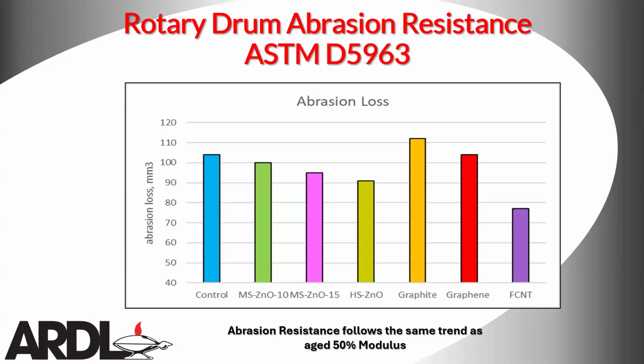But remember how I said stiffness is going to relate back to our abrasion resistance. So when we're looking at the rotary drum abrasion resistance, here we're looking at abrasion loss. So what that means is that a lower number is going to equal better abrasion resistance. And if I look here, I see the same trend. I see my higher level of zinc, my high surface activity zinc, and my functionalized carbon nanotube have the least amount of abrasion loss, or the best abrasion resistance, compared to all of the other materials. And so once again, I thought this was a very neat correlation. And here you're actually seeing that with all of the compounds, you saw a reduction in abrasion loss with the exception of the graphite and the graphene.